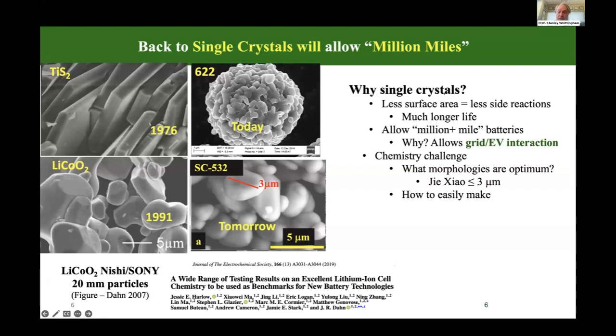So why go to single crystals? I've already mentioned less surface area, less side reactions, longer life, and as Jeff says, this in principle allows million-mile batteries. What it really does is allow your vehicles to be attached to the grid at all times when the vehicle is not actually moving. So it can act as grid storage, grid stabilization, and provide power to your house. The challenge here is, Jeff also showed that if you keep the size under 3 microns, they will not crack. So the big issue with the meatballs is they crack as you cycle them.